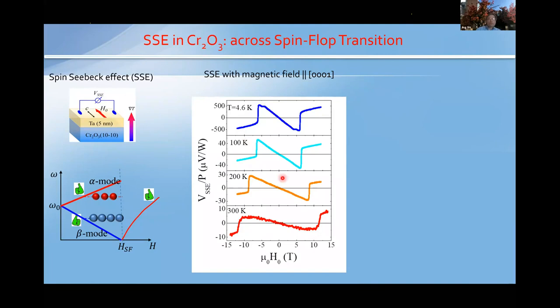Okay, so these are the data taken at different temperatures. At low temperature, we see here the spin flop transition is around 6 Tesla. We see clear sign change here below the spin flop transition and right above the spin flop transition, indicating the handedness switching from left hand to right hand. So this is consistent with our earlier picture related to magnon spin Seebeck effect.